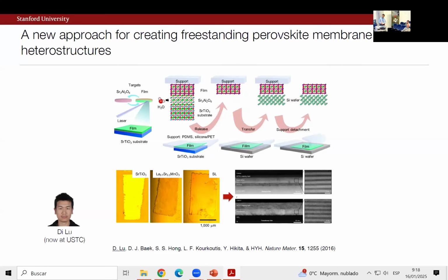And so we and other groups have developed various recipes for this kind of stamping, if you will, with various polymers and so forth. We borrowed a lot from the advances made in 2D systems like graphene. But you can see even from the early days, it's a little bit rough, right? These are literally just cut pieces of substrate, but you can see membranes that are already exceeding a millimeter lateral scale.